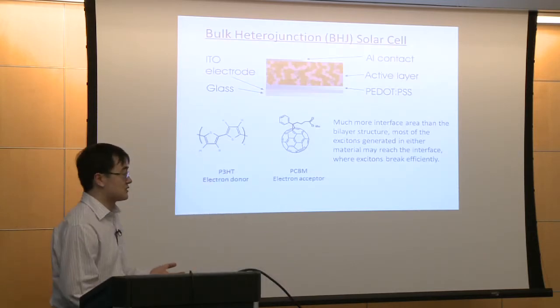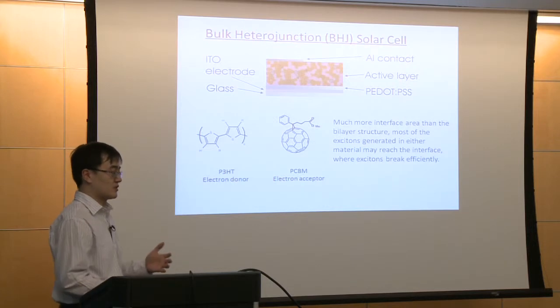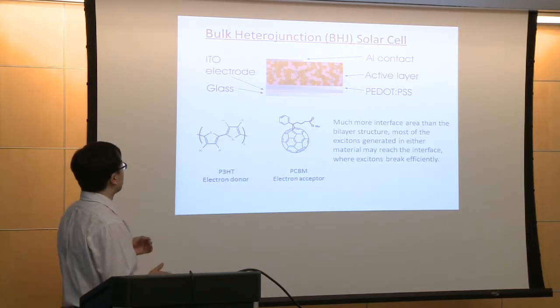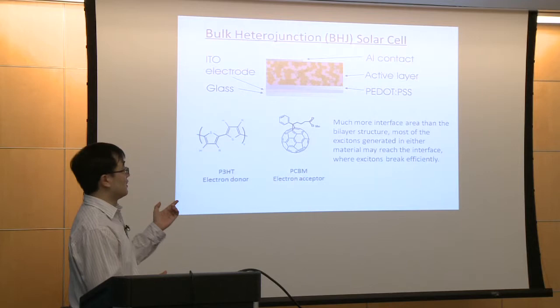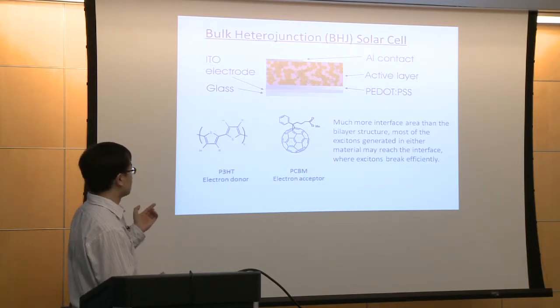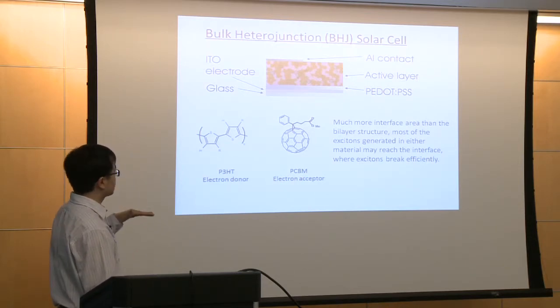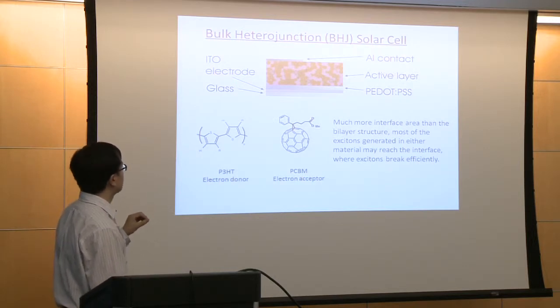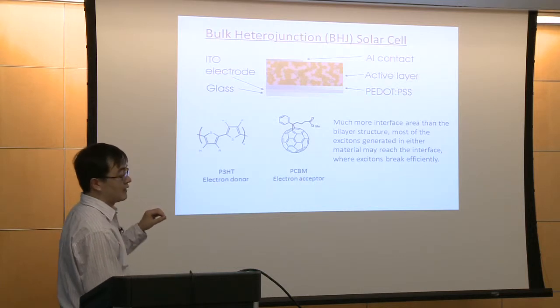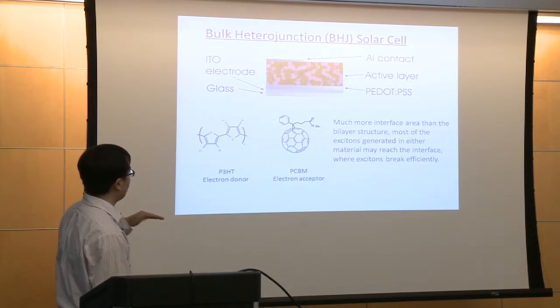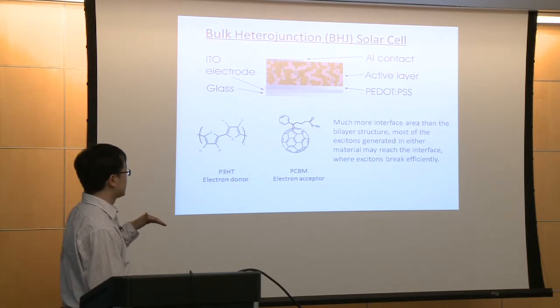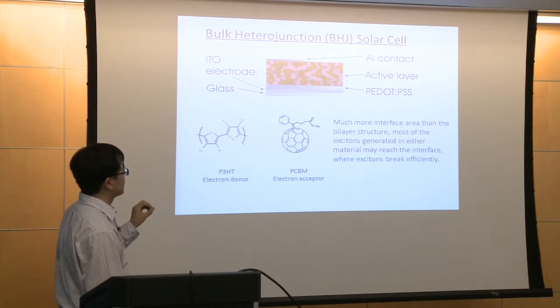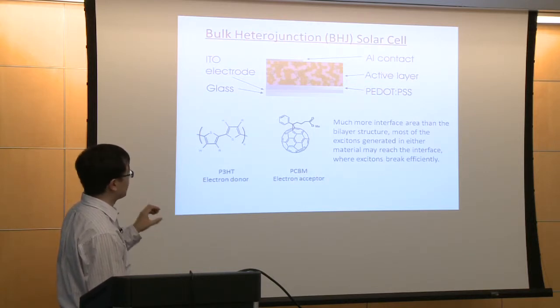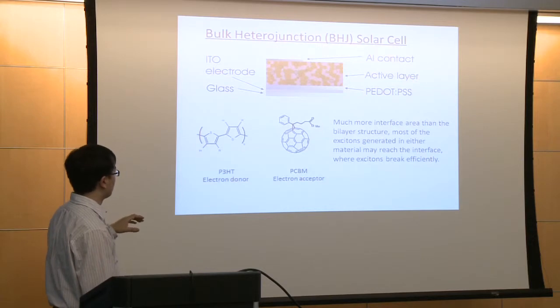So here I will introduce the bulk heterojunction solar cell, which we are doing research on. This is the structure of the state-of-the-art bulk heterojunction solar cell. Basically, it uses glass or some other substrate as the bottom layer. Then they coat indium tin oxide as the electrode on top, and then they spin cast a PEDOT:PSS layer as the hole conductive material, and they spin cast an active layer on top. And finally, they have an aluminum contact on top.